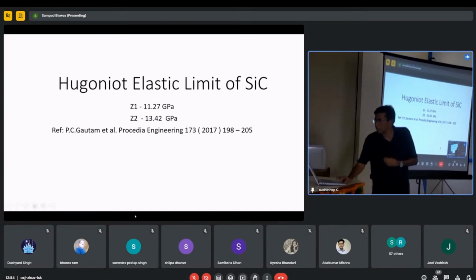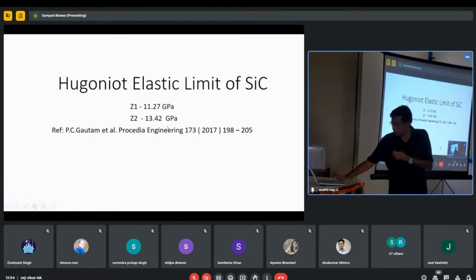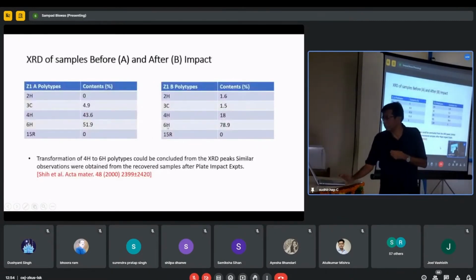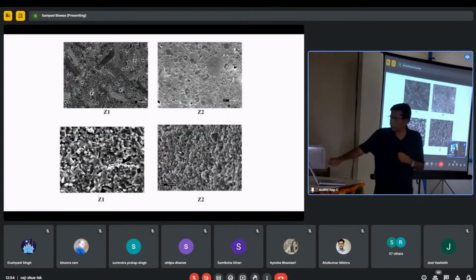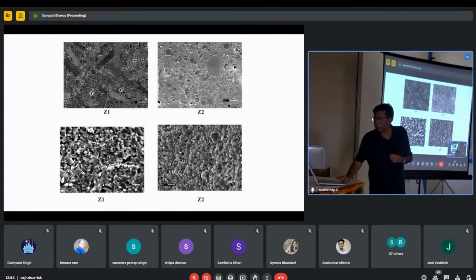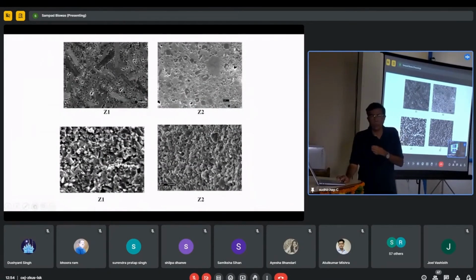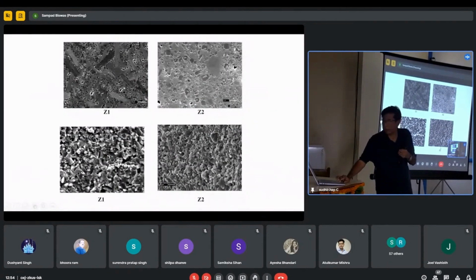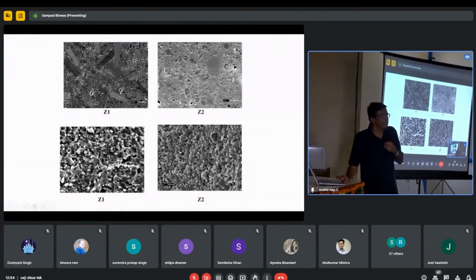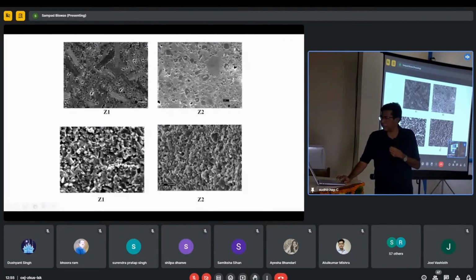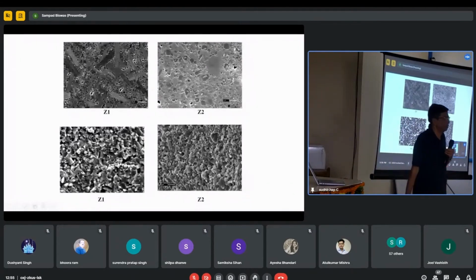So in case of one, we have seen 11.27 GPa. The other one is about 13.42 GPa. Also a little bit on how the microstructures are. So these are the two microstructures. You can see that here longer grains are obtained. These grains, we believe, are mainly 6H grains, and this elongation has been taking place in one microstructure. The same silicon carbide, when processed in a different way, the grains become very small.